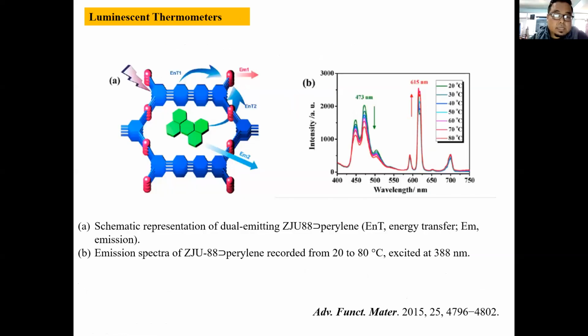Similarly, we have another luminescent MOF, ZJU88. In ZJU88, perylene, which is already known as a very highly fluorescent material, is encapsulated, and it shows a very linear dependence of the 473 and 615 nanometer emission bands. 473 is for the perylene molecule, and 615 is for the metal organic framework. So we see a very linear correlation between the emission decrease of 473 and the emission increase of 615, which can be used as a ratiometric thermometer, because the temperature dependence is almost linear.